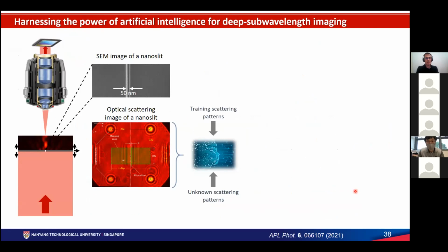Another component I want to use in building this technique is the power of artificial intelligence for sub-wavelength imaging. Very recently, we developed a technique where we decided to image very simple objects. We started with a very simple geometrical object, 1D, a nanoslit of varying size, and we illuminate with plane wave illumination. We collect the scattering pattern, we move the position of the slit so we can collect at different heights and different positions, and we create enough scattering events to be able to feed an artificial neural network. After the network has been trained enough, you can feed it scattering patterns from slits that the neural network has not seen before.